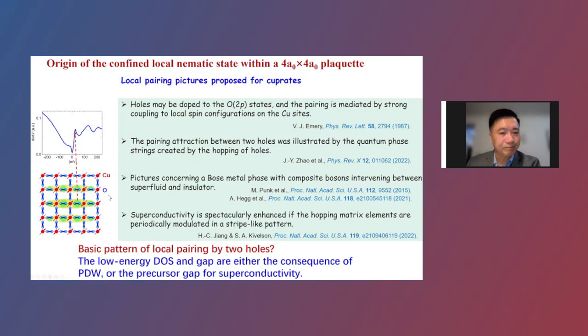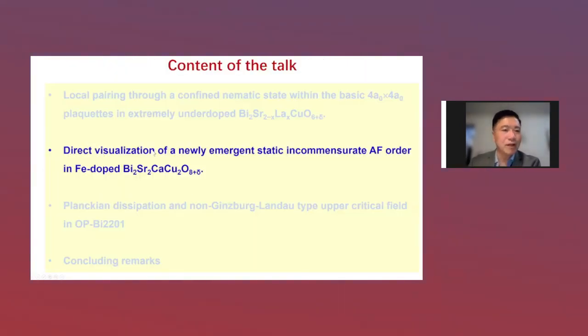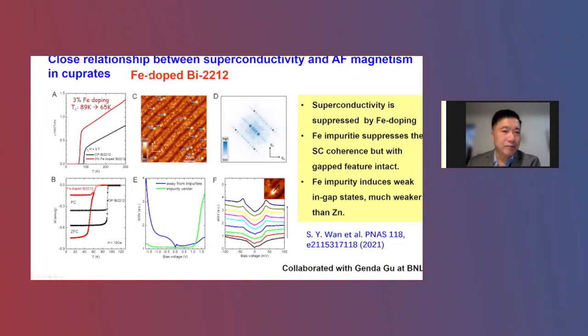Okay. So then I come to the second piece of work. The second piece of work is optimally doped BISCO 2212 with iron doping. Using 3% iron doping, we suppress the Tc to about 65K. Here shows the resistivity. And by using the magnetization data, with the Curie-Weiss fitting, we found that the iron yields a magnetic property. And because of the tunneling on the iron impurity, it shows this kind of tunneling spectrum. So we can use a high energy tunneling spectrum to find the iron spots here. And on the iron spot, we see that the gapped feature on the tunneling spectrum is still there.